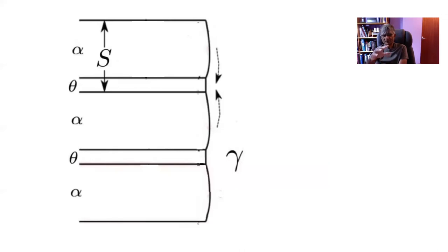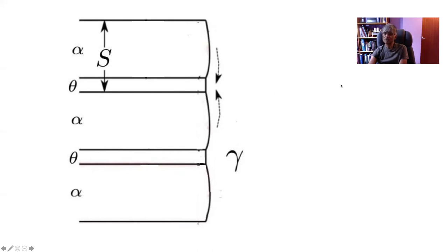In a simplified mathematical model, pearlite consists of alternating layers of cementite and ferrite with interlamellar spacing s. Because the carbon partitioned by the ferrite into the austenite is absorbed by the cementite, diffusion runs parallel to the interface through the austenite rather than normal to it, and therefore there is no net change in the composition of the austenite away from the interface, at least as far as iron-carbon alloys are concerned.